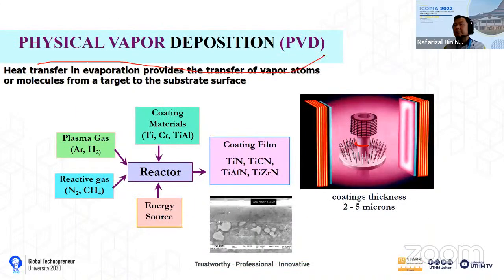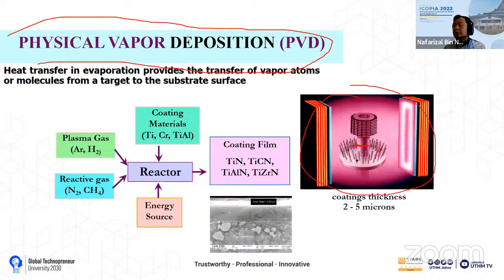Okay. PVD is physical vapor deposition. It's very common for coating applications. On the right here you can see they want to put the tools, the drilling tools, inside here so they can deposit titanium. They put the titanium plate at the right and the left here. They put argon gas inside and then discharge so that the titanium ions will evaporate and deposit on the drilling tools. So they will create a hard coating on the drilling tools. The materials they normally use are titanium nitride, titanium carbon nitride, TiAlN, titanium aluminum nitride, and TiZrN. So normally the nitride film is a hard coating material.